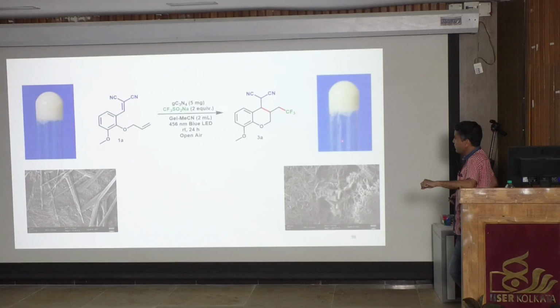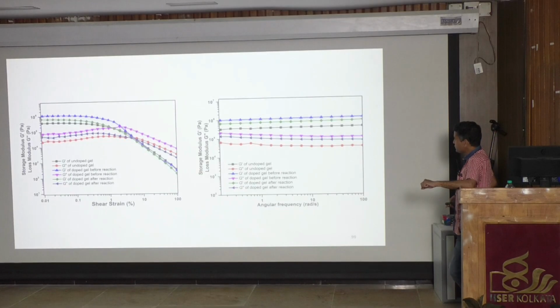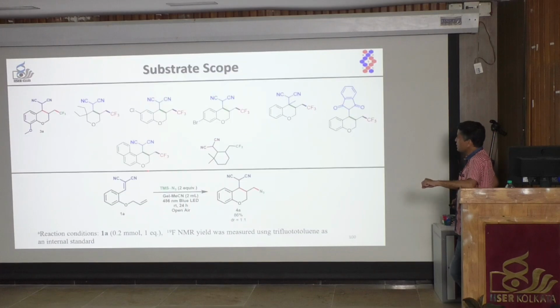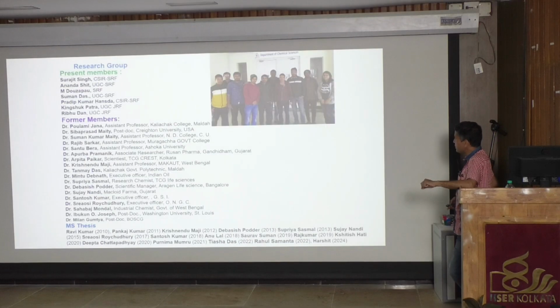95% conversion. And this is the morphology of the gel and the reagents before reaction. This is after reaction. So the morphology of the gel is almost intact. And we have done rheology before gelation, after gelation, before doping and after doping with the reagent, and after irradiation of the light. And this is the substrate scope. So we can do this reaction with many substrates, and they are giving very nice yields.